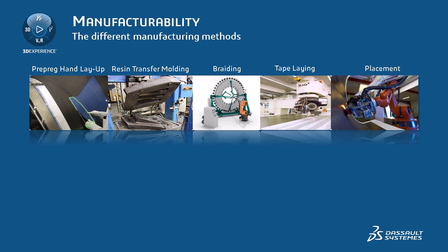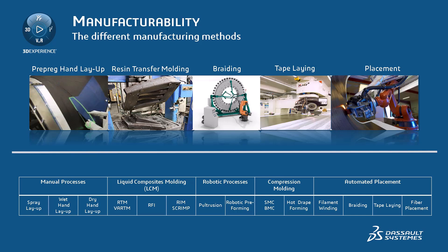Let's introduce the manufacturability of composites. A large number of composite manufacturing processes have been developed over the last 40 years, including contact molding, compression molding, vacuum bag/autoclave molding, rotational molding, resin transfer molding (RTM), tape wrapping, filament winding, pultrusion, expanding bladder molding, and more. All these processes share common characteristics: the reinforcements are brought into shape in a tool or mold; resin and fibers are brought together, possibly under elevated temperature and pressure to cure the resin; and the part is stripped from the mold once the resin has cured. The different fabrication techniques can be classified as direct processes — like RTM, pultrusion, or contact molding — that use separate fibers and resin, or indirect processes that use fibers pre-impregnated with resin, like vacuum bag/autoclave molding or compression molding.